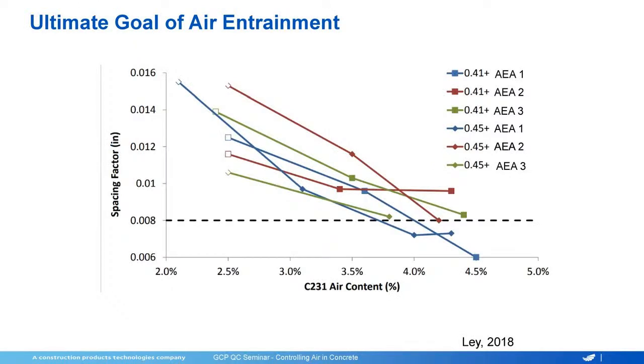And this is just an example, really, of different readings with different air entrainments at different water cement ratios. So same mix, different materials, and we're getting different results. And again, you can see that spacing factor often goes along with how much air we get. So the more air we get, we tend to get smaller bubbles.